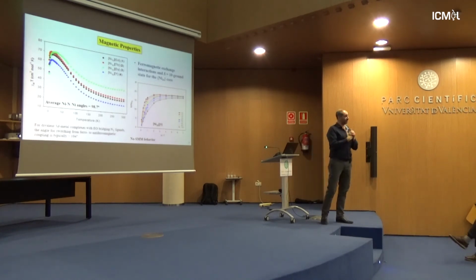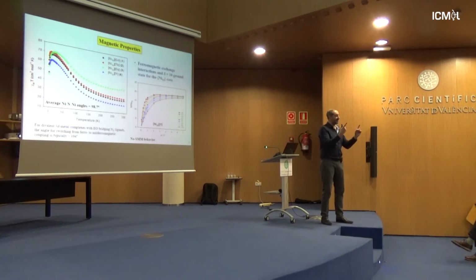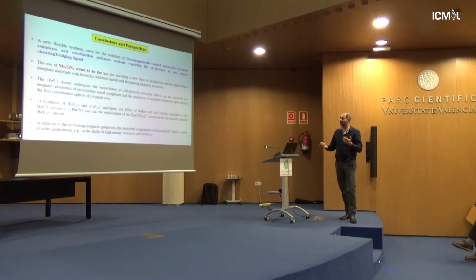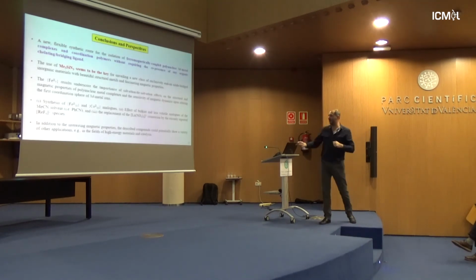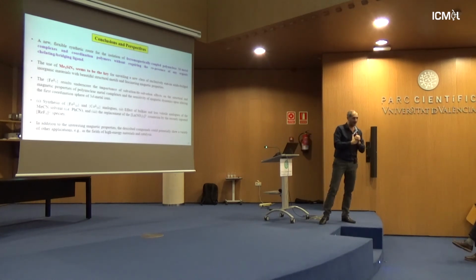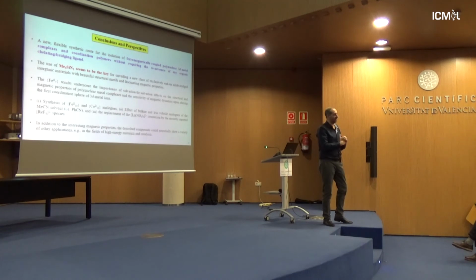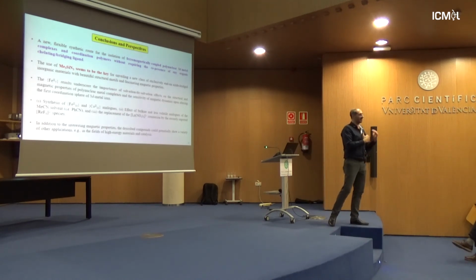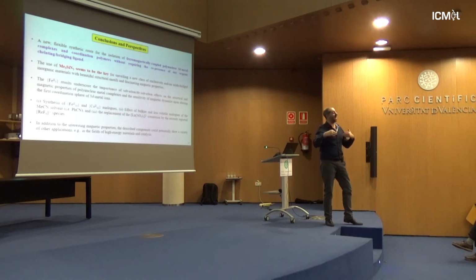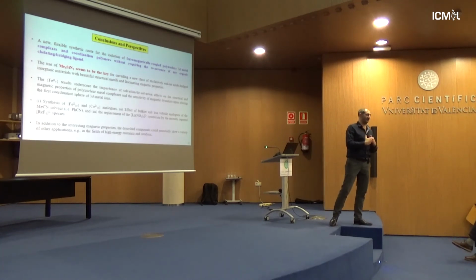We were not able, because they are not single molecule magnets, to see dynamics as we saw before with the iron 7, the two processes which could rely on solvation-desolvation effects. So we were not very keen on this case here. So in conclusion, we saw a variety of different compounds which in our opinion demonstrate the usefulness of that synthetic approach, which I would like to call a guaranteed synthetic approach to high-spin molecules and potentially to molecules with quite different or rare SMM properties, like the two relaxation processes that we saw before.